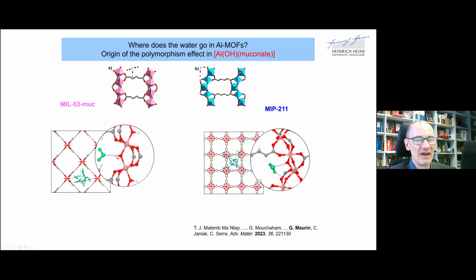And these are in the aluminum MOFs the bridging hydroxyl groups, which bridge between the aluminum atoms. So in this MIL-53 muconate polymorph, it can only accept a hydrogen bond from one hydroxyl group, because in here the hydroxyl groups are trans-oriented. So the next one from the next bridging unit is too far away.